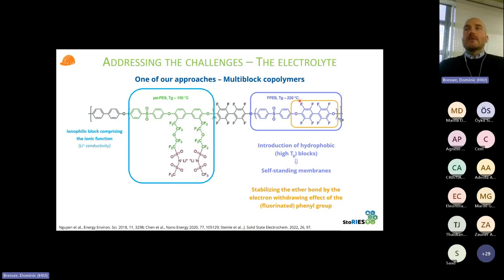The fluorine here in the backbone, however, does also play a role for the reactivity with the lithium metal, in the sense that if you have the fluorine here in the backbone, you form a very lithium fluoride rich solid electrolyte interface in contact with the lithium metal. If you don't have the fluorine here, you don't have this LiF formation, or to much lesser extent, and you see this in a reduced stability of the polymer in contact with the lithium metal, and then shortened cycle life or increasing polarization. So it's important for both, right? The stability towards oxidation, thermodynamically, so to say, and kinetically towards reduction by forming a lithium fluorine-rich interlayer.